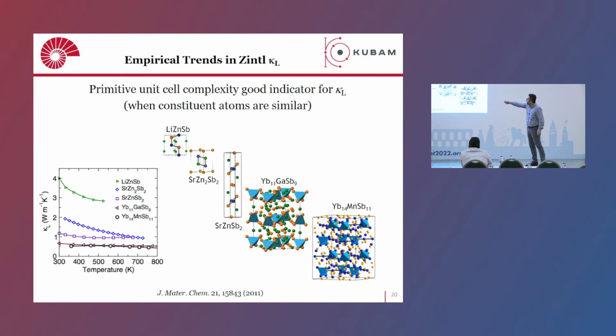You can see that this is only 6 atoms per unit cell, and you increase the unit cell size, you introduce different, let's say, local environments. Here you can reach 208 atoms per unit cell. Large unit cell, very different local environment, leads to lower thermal conductivity, experimentally shown. So this is lithium zinc antimonide, and this is for the ytterbium manganese antimonide. So this is extremely low lattice thermal conductivity, and you don't need to do anything. This family of materials has a complex unit cell which already shows low thermal conductivity inherently.